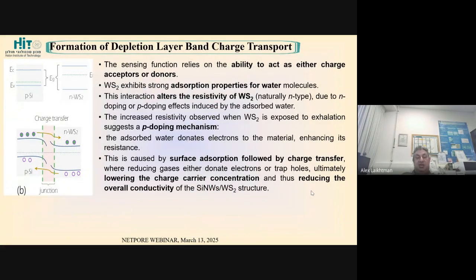And this is my last slide. So some explanation. We consider that there is a depletion layer band charge transport in the case of P-type silicon nanowires and N-type WS2, even when it's not doped. So we consider that the sensing function relies on the ability to act as a charge acceptor or donor. WS2 exhibits strong adsorption properties for water molecules, because remember, breath test is always performed in the atmosphere.